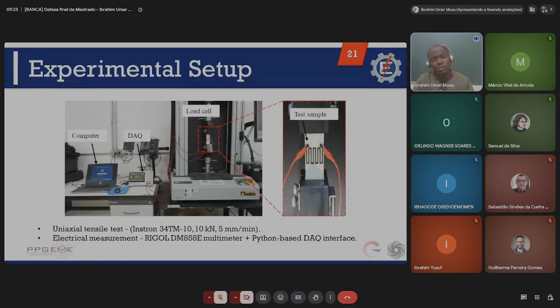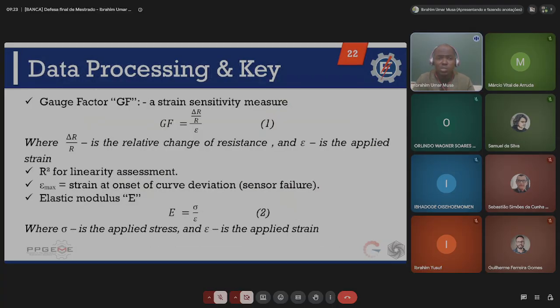We have our experimental test setup as presented by this image showing the data acquisition system, the load cell, and the test sample placed between the jaws of the load cell, as well as the data acquisition device. Of course, the load applied was quasi-static at 5 millimeters per minute. And the gauge factor was evaluated using equation 1, the linearity assessment as R squared, and the maximum working strain identified at the onset of the deviation of the characteristic curve, the resistance-strain curve. And the modulus of elasticity was also evaluated using equation 2 as presented on this slide.